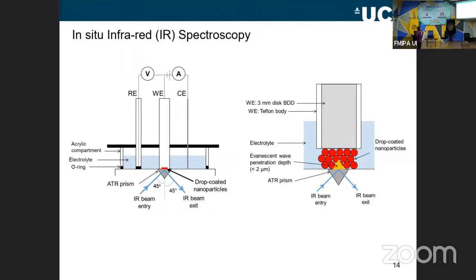So what we do is we put our sample on an electrode again, so it's just here, and we push it very close to the surface of the prism, and then we clamp an electrochemical cell on top, and then we will hopefully measure the infrared spectrum of whatever is just above the prism. And this here is a kind of bigger picture of that region. So you can see here the infrared is coming in, it's reflecting on the surface and coming out. And we have this bit of wave here, which is called the evanescent wave, which penetrates just above the surface of the prism. And it's able to measure a spectrum of whatever particles are there, and also the solution species that it's dissolved in, because it's in an electrolyte. And it's on the surface of an electrode, so we can apply a potential as this happens.